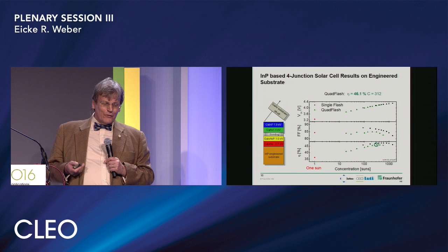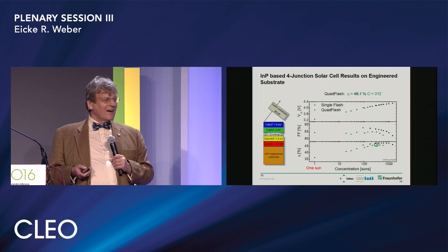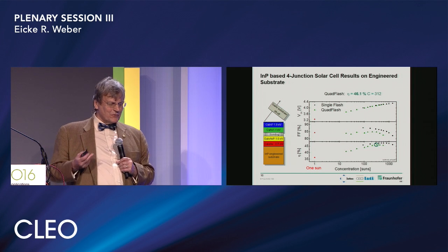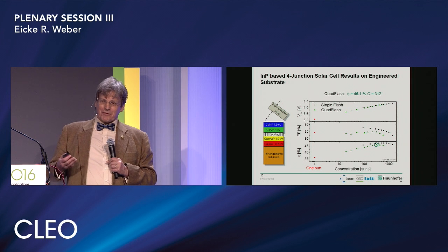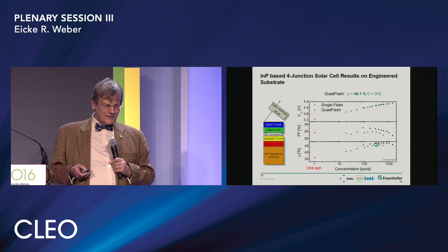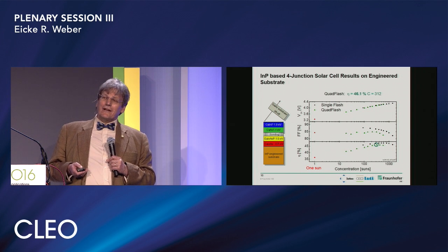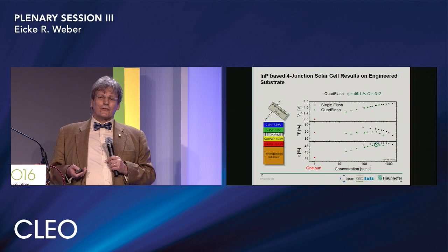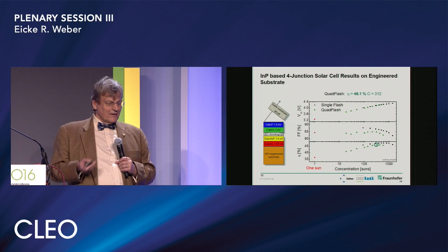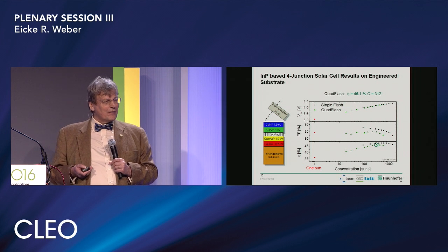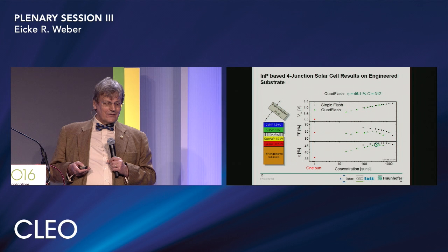46.1% at ESE, 46.0% at AIST, the sister institute in Japan, which did the calibration together with ESE. So we have exceeded 46%. And we believe that we are very well on our way towards 50%. The structure itself has a maximum of the order of 60%. So there are still possibilities, and in any case, I would say it is an amazing number which can be reached in this technology.